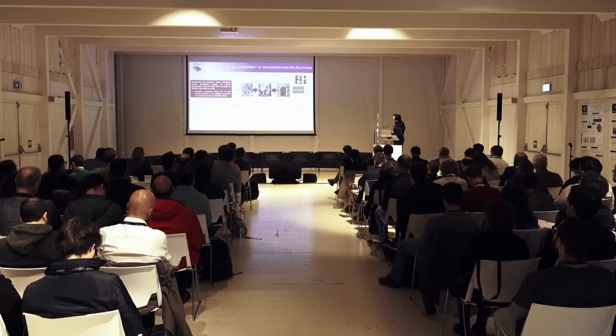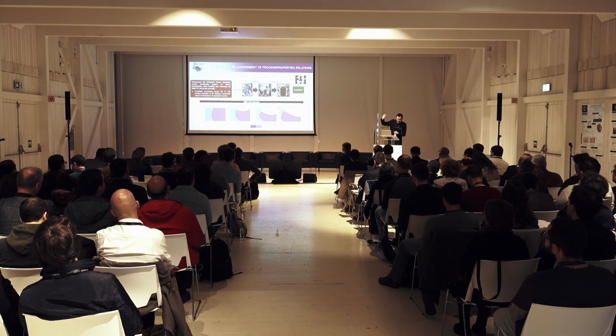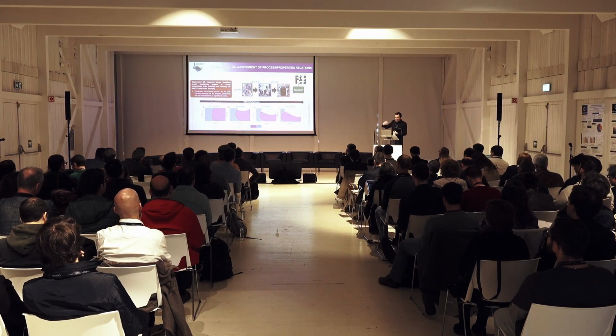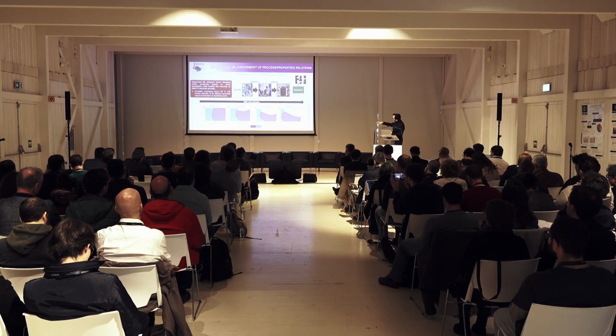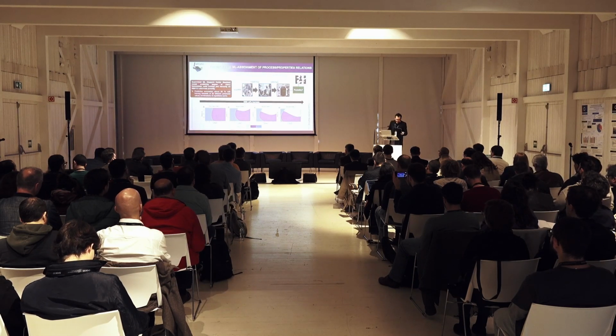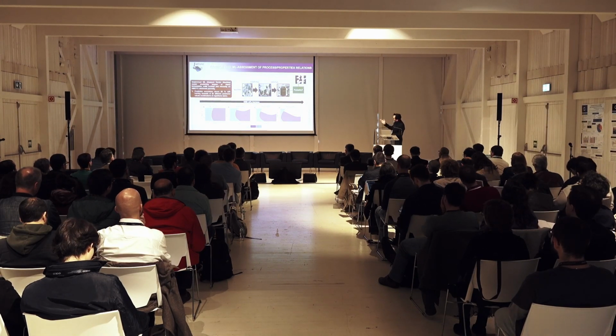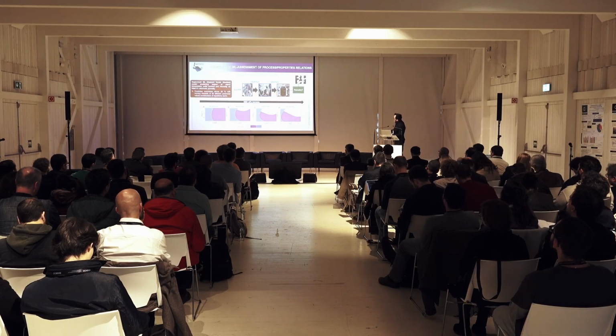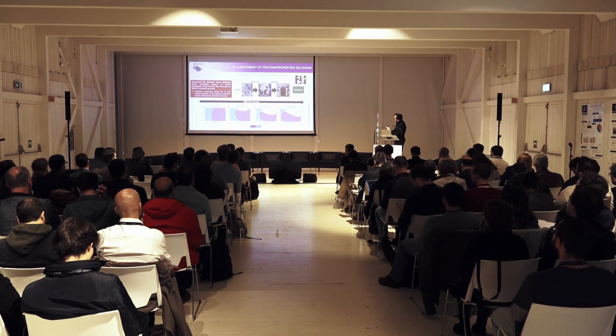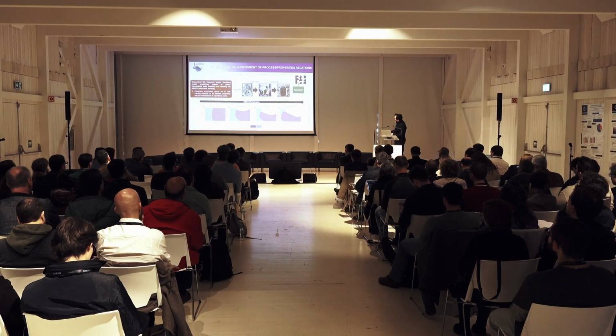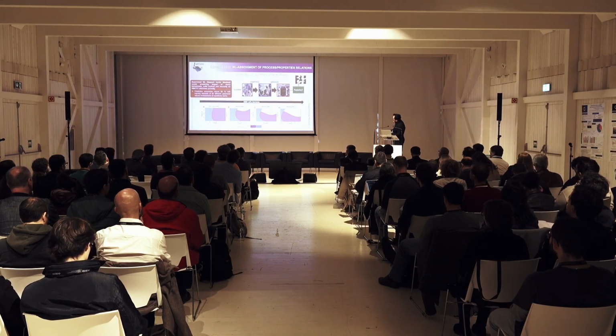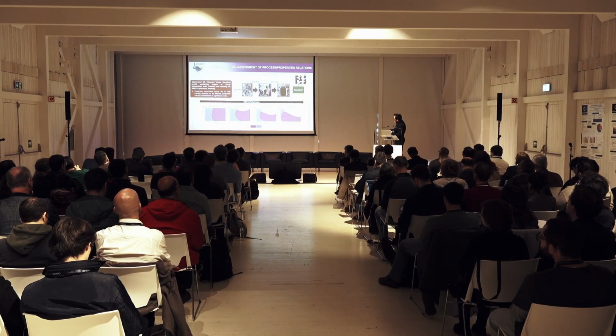By applying support vector machine, we actually convert this messy cloud of points into something that is more visible and more understandable. These are so-called boundary plots, which look more like phase diagrams in solid-state chemistry. But this is not a solid-state chemistry problem, this is a manufacturing problem. And here, basically, what we can see is that it's impossible, according to this support vector machine output, to make electrodes with low porosity if you have a formulation of 92% of NMC. However, it becomes possible when you increase the amount of active material in the slurry. You see these white zones appearing here.